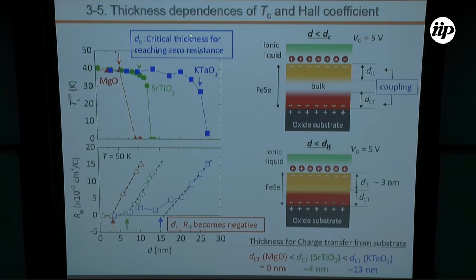For both cases, the critical thickness of the superconducting transition and the critical thickness for the sign change of the Hall coefficient increase in the order of MgO, strontium titanate, and potassium tantalate. And you can note that the slope of the Hall coefficient is almost the same irrespective of the substrate materials, implying that only this middle bulk region decreases by etching. By assuming that the depletion layer, the accumulation layer from the top ion gate, is almost 3 nanometers, we can easily calculate the charge transfer layer's thickness. That is 0 nanometers for MgO, 4 nanometers for strontium titanate, and 13 nanometers for potassium tantalate.